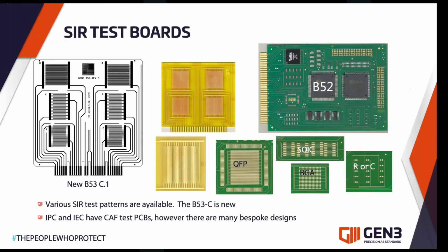So test pattern is a critical part of our choice. And on this slide, we just show you that there's no one size for SIR patterns. They come in all shapes and all sizes. So the B52, which is for a process validation experiment, that B52 being an IPC code, we get all the different SIR patterns that fit to those particular components. Whereas the pattern on the left is for the newest pattern that's available, B53, which is for flux and coating qualification, and that has a 200 micron gap pattern, the B24 500 micron gap pattern, and the B25 318 micron gap pattern.